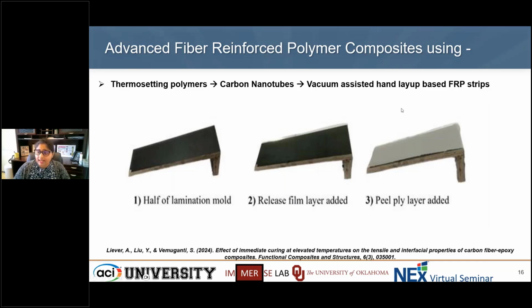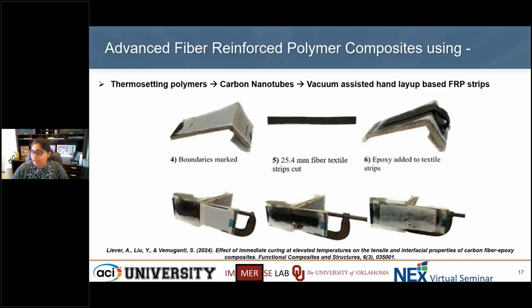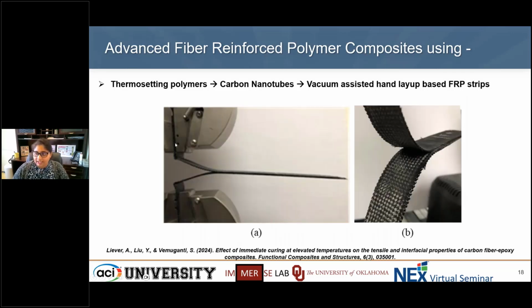To understand that, we performed an ASTM peel ply test. For that, we basically bonded 2 layers of carbon fiber with these carbon nanotubes, and we performed these tests on a peel type specimen. The specimen is more evident in this particular picture. If you see, it's more like a T-flange. And the peel is obtained by using a tensile test setup and pulling one end of the flange.